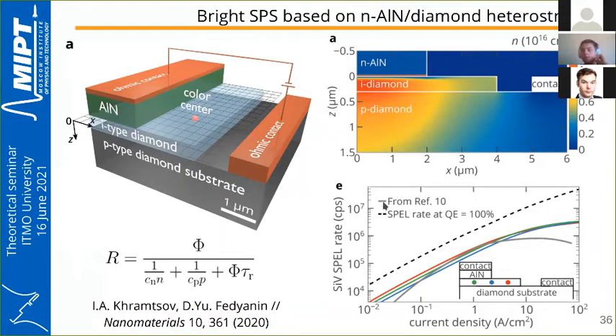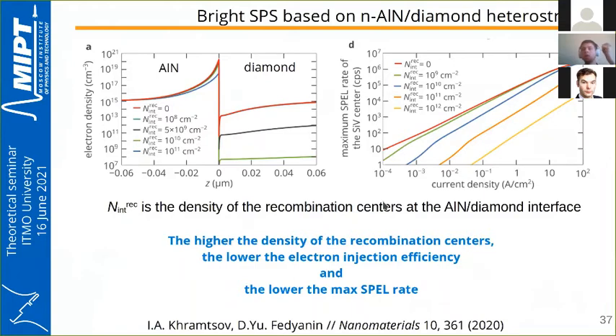These are very interesting results, but the problem is that aluminum nitride and diamond have a bit different lattice constants, which leads to a possibly high density of interface recombination centers. Here you can see the distribution of electrons at the interface between the aluminum nitride and diamond.